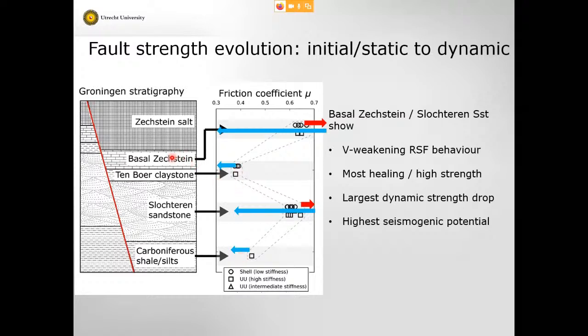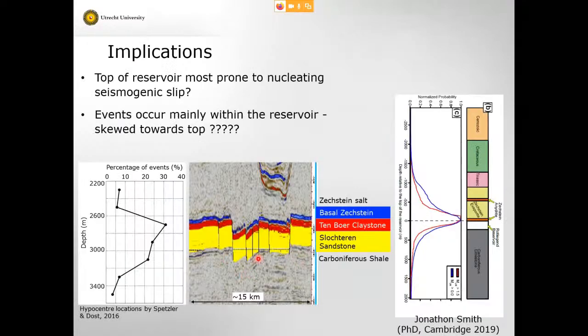The other rock materials in between, their strength doesn't do too much. So that leads you to think that sandstone and the basal Zechstein and mixtures are going to be the things which are very sensitive towards earthquakes. And indeed, this is a bit controversial and it's also very preliminary. The distribution of earthquakes recorded within the reservoir in the last few years suggests a bit of a skewing towards the top of the reservoir, which would be consistent with this anhydrite carbonate evaporite material and the sandstone being the most sensitive to initiating earthquakes.